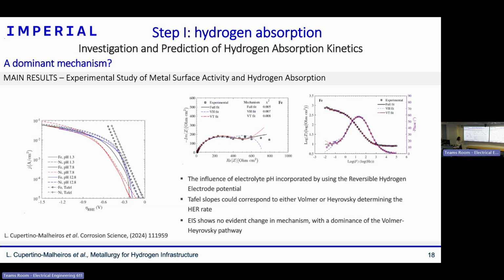All right, so overall, by doing experiments related to the metal surface activity, I could quite easily incorporate the effect of pH on the kinetics of hydrogen production, and also see that the dominant mechanism was Volmer-Heyrovsky for all the conditions tested, so a wide range of potential and pH.